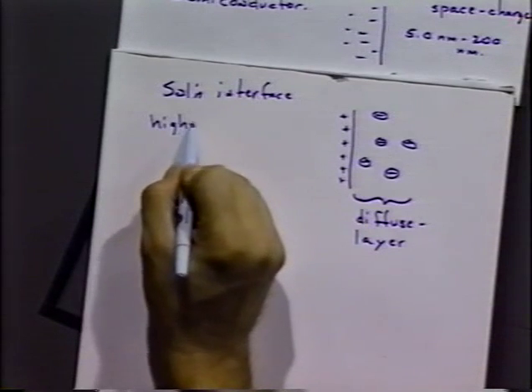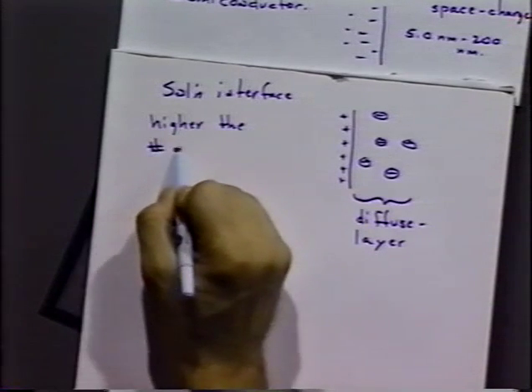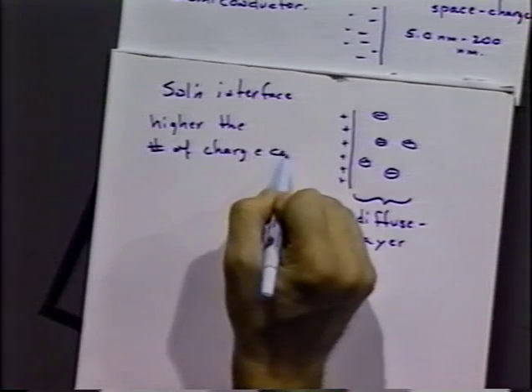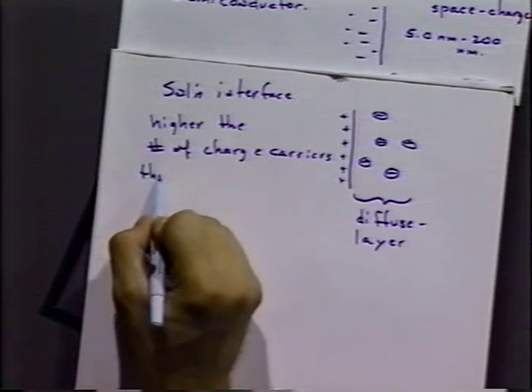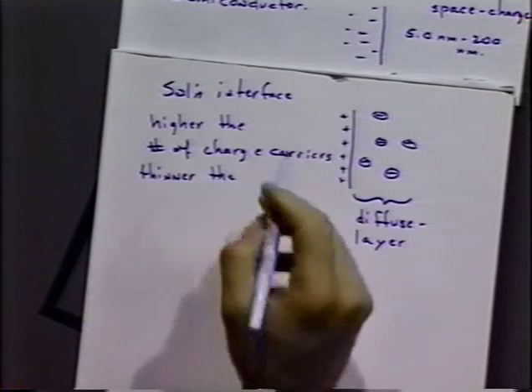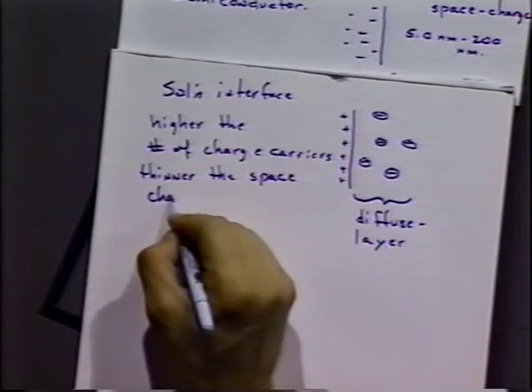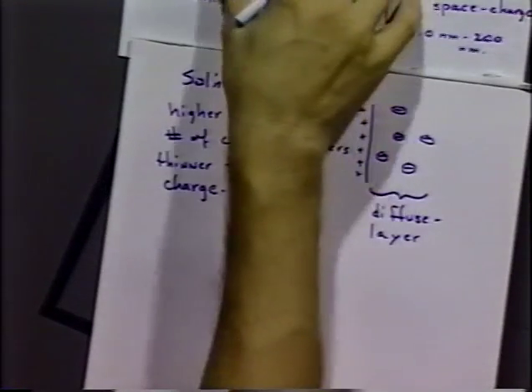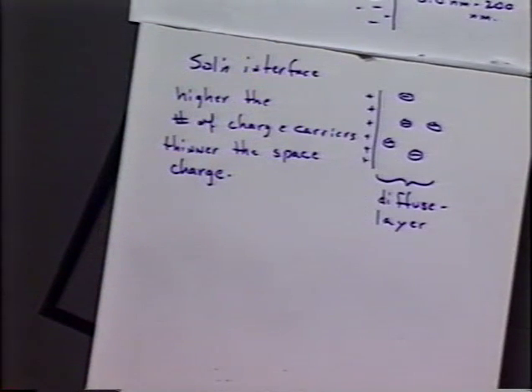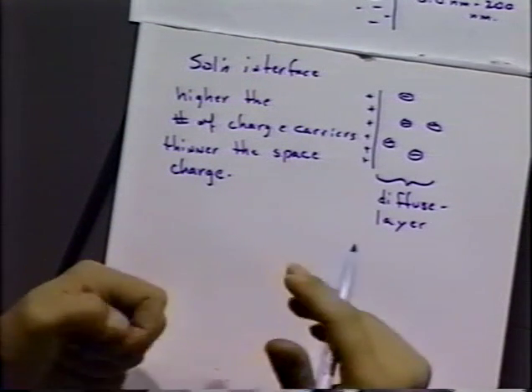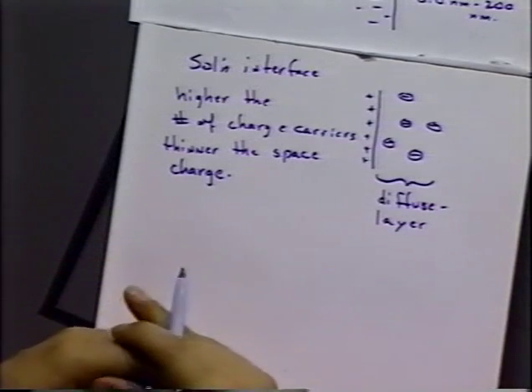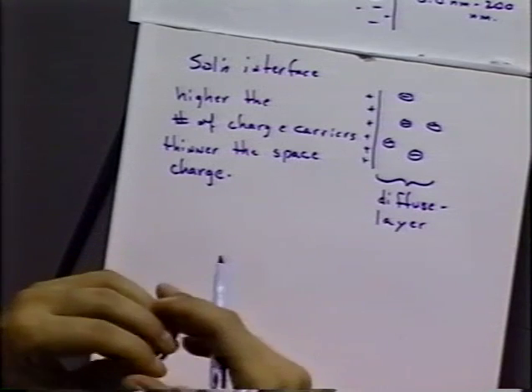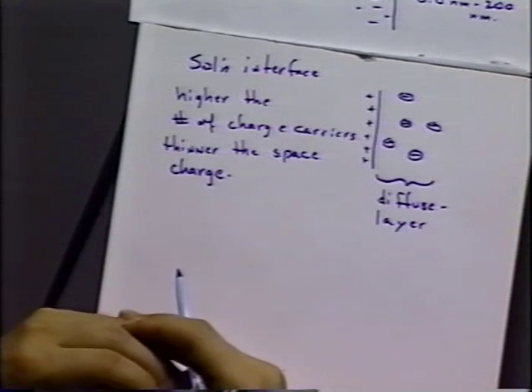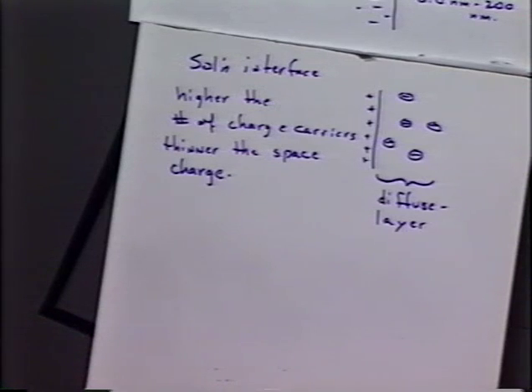So we can make a general statement. The higher the number of charge carriers, the thinner the space charge. A diffuse layer in electrochemistry may extend out, say, 200 nanometers with a very dilute solution of electrolytes, say a few millimolar concentration of potassium chloride, to 5 nanometers or so for, say, a 1 molar or a saturated potassium chloride solution. So one way to reduce the space charge effects is to make the concentration of charge carriers higher.